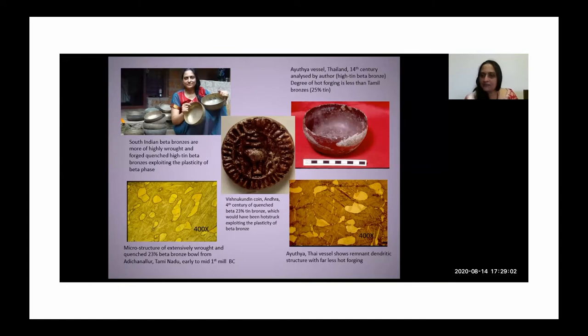And if you look at that microstructure, however, you do see the formation of a little bit of the martensitic beta phase, but there is a lot of the retention of the as-cast dendritic structure. So it has not been forged to that extent, but it has been cast and quenched so that at least a prevention of the embrittling alpha plus delta eutectoid has been done. So this is more lightly worked and cast and quenched, but it's not extensively wrought and forged, as we can see.